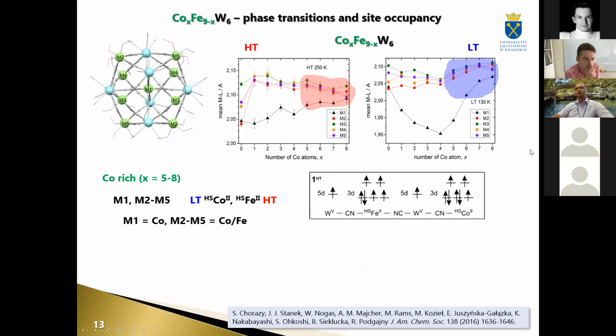But the most important information can be drawn from the temperature variable structural data. So now let's focus on cobalt-rich phases. Where no transition is observed, these are valence electronic structure, and looking at the distances between 3D metal ion and nitrogen or oxygen, we see that indeed here we have the clear situation where these numbers, 2.10, show us that there is no transition.